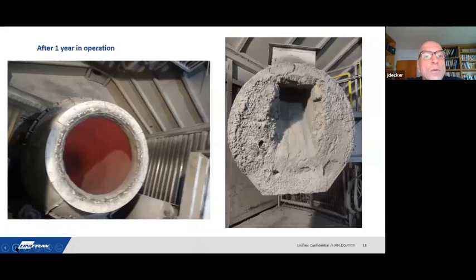So this is after 1 year in operation. This furnace has been in operation now for 3 years, but this picture was taken after 1 year, and you see that the drum itself is absolutely clean and looks impeccable. The door has some material adhering to it, which is not unusual. And I think they did some maintenance on the door after 1 year, but it's also the first lining still in there after 3 years.